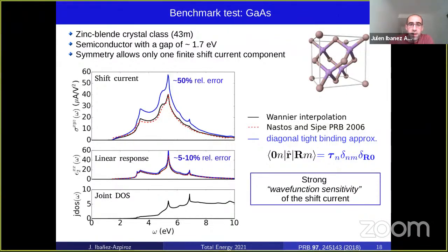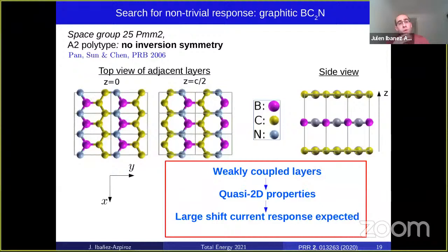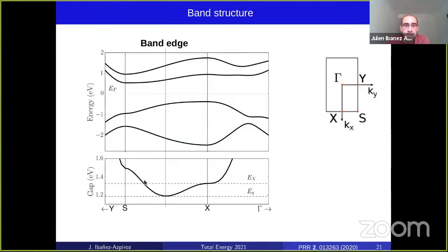In the remainder of the talk, I would like to now focus on the next material and more interesting system that is a second application of the method. And this is graphitic BC2N. This material is a layered semiconductor that has a broken inversion symmetry. Because of its structure, it contains weakly coupled layers, and we can expect quasi-2D properties, so again we can expect a large shift current response.